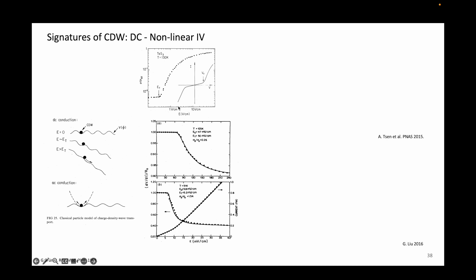Similar to the washboard potential of Josephson junctions, charge density wave also has a washboard potential. By applying a bias voltage between the two ends, the washboard potential can be tilted. This shows up as a non-linear IV where until the threshold voltage, V_t, the conductance is very small and linear. And as you reach the threshold voltage, the washboard potential is tilted so much that the ball in this picture really rolls off to the side, resulting in much higher current.